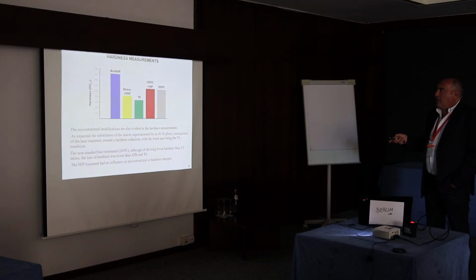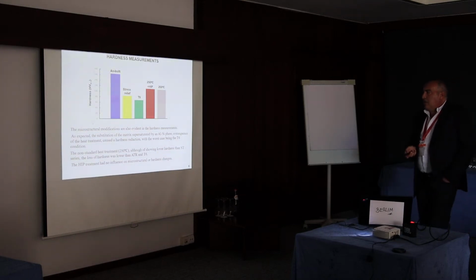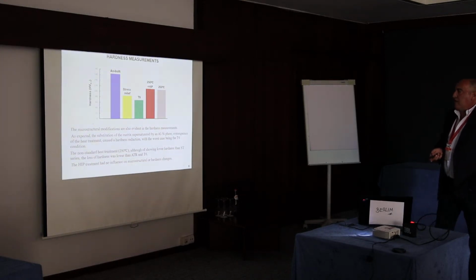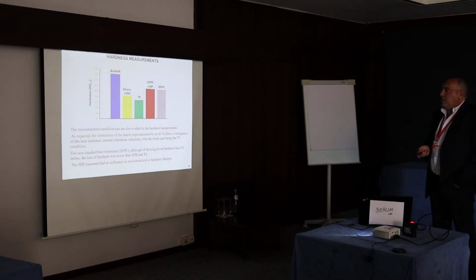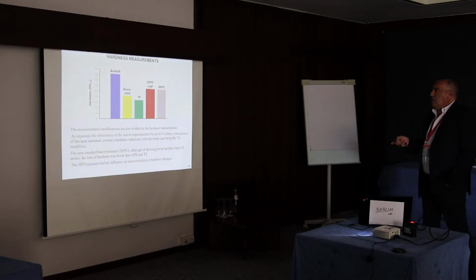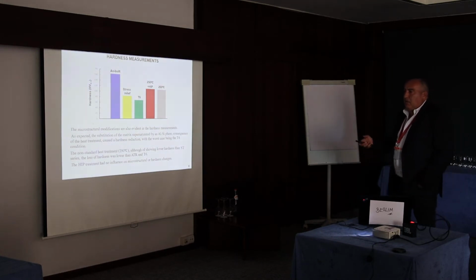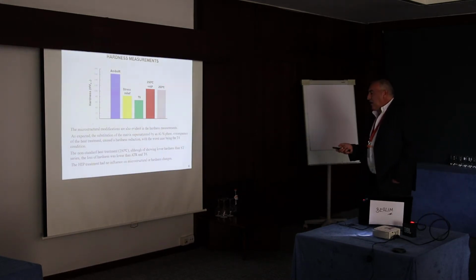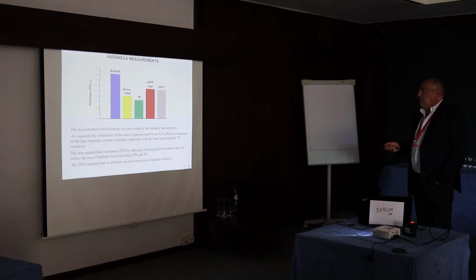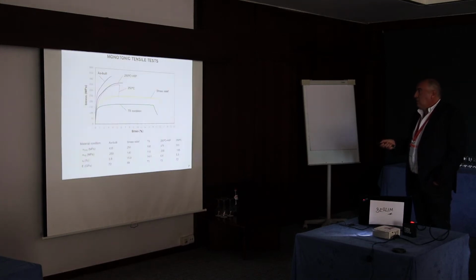When we pass to the non-standard tests, although the hardness is lower than for the as-built, the loss of hardness was lower than for these 2 treatments. And the HIP treatment compared to the 250 treatment, they are made at the same temperature, but the HIP has 100 megapascal pressure, with no significant hardness change.